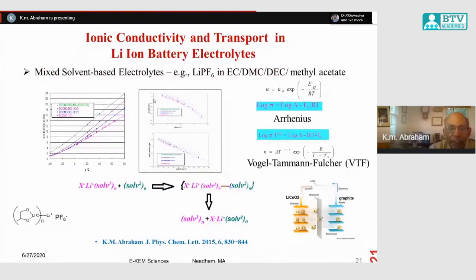So this shows what people do. As I said, a battery has to work from very low temperatures to very high temperatures. So you look at the ionic conductivities of these electrolytes as a function of temperature, in this case from minus 40 degrees to 80 degrees centigrade. We did this study with different mixed solvent electrolytes: EC, EMC; EC, DMC, DEC. That is ethylene carbonate, dimethyl carbonate, ethyl methyl carbonate. And then another one where we made a four-solvent mixture.